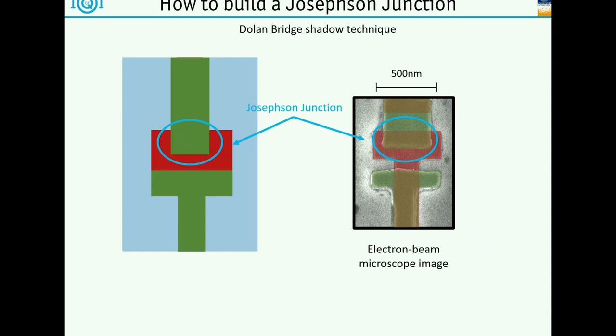So with this technique, we can create junctions which are a few hundred nanometers in size. Here you have a scale bar. This distance here is like 500 nanometers. So this is like 100 to 200 nanometers. You can make them even slightly smaller if you want to.